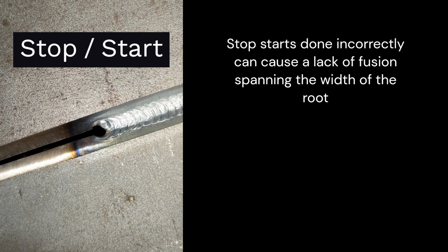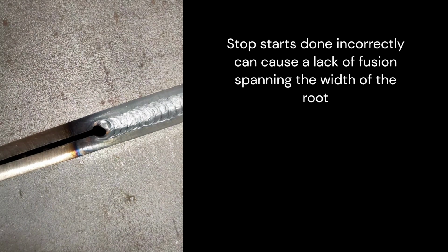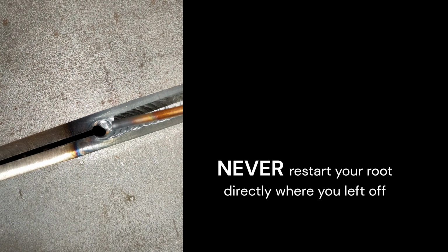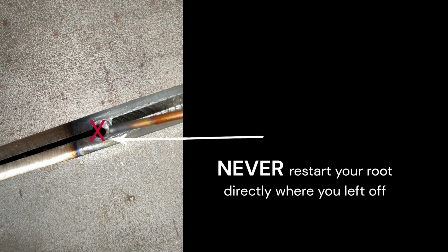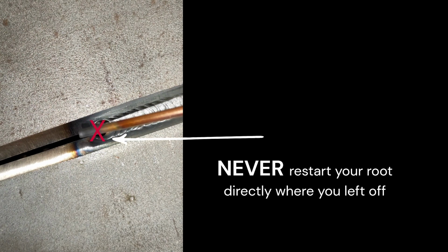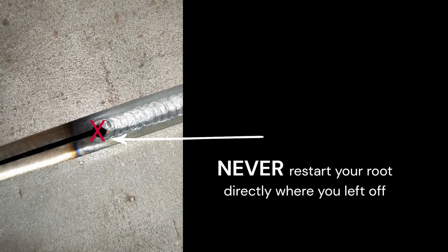At some point during a root weld, you'll have to perform a stop-start. This is a common X-ray failure point, due to a lack of fusion between the points you left off and restart the weld. Do not restart at the very end you finished and just carry on. This is where the lack of fusion occurs and it can show on X-ray and it will be a fail.